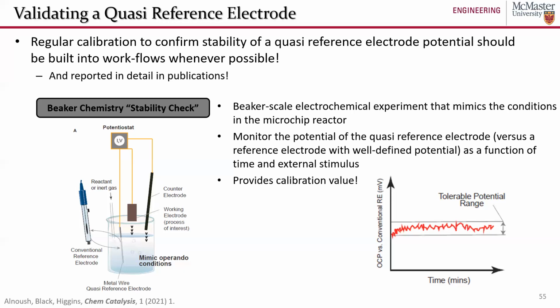The other thing you can do when you set up this beaker-scale chemistry is put in a conventional reference electrode and just measure the potential difference between your quasi-reference electrode metal and the conventional reference electrode. And then all of a sudden you've got a calibration value that you can use when converting your electrode potential measurements.